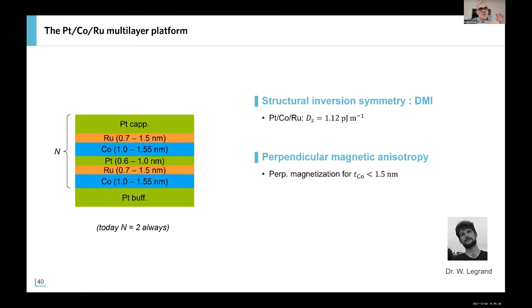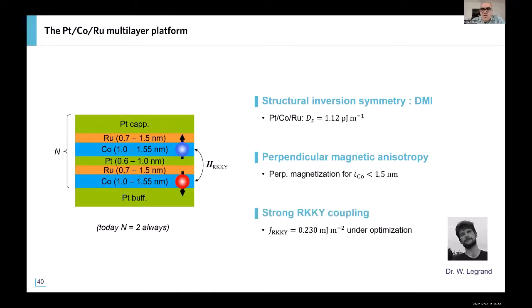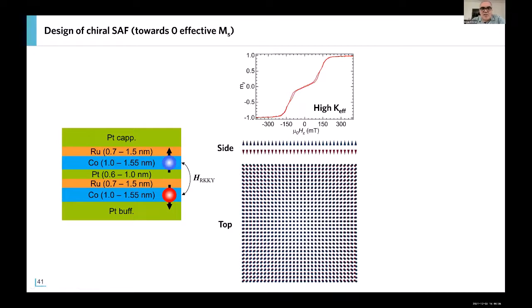And what is important to stabilize the antiferromagnetic skyrmions is to be very close to a compensated effective magnetic anisotropy. And we can very well control the RKKY indirect exchange interaction between two magnetic layers through this spacer layer. And we can get the layer thickness for which we maximize the coupling to be antiferromagnetic. Okay, so doing so, what can be expected? If you have two layers that have a very strong perpendicular anisotropy, you will have, this is a top view, this is a side view, you will have two uniform domains, but antiferromagnetically coupled at each position.